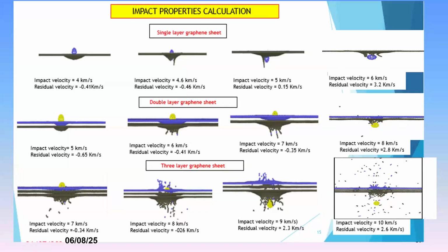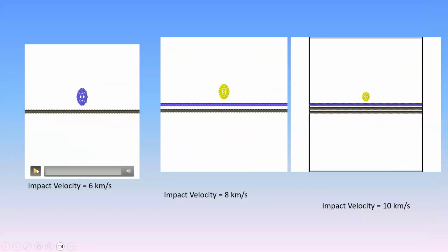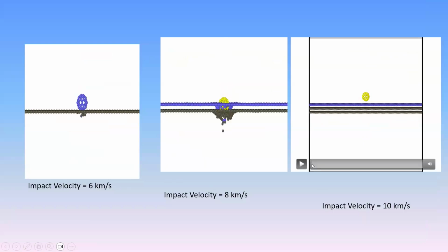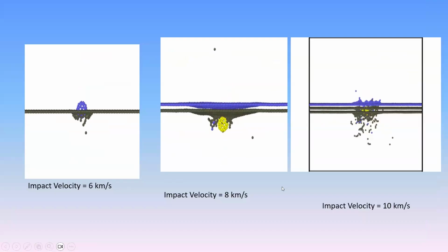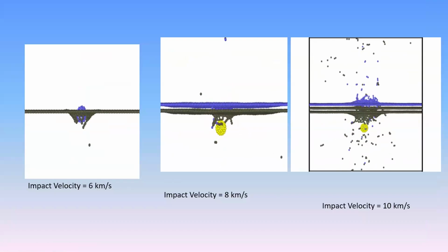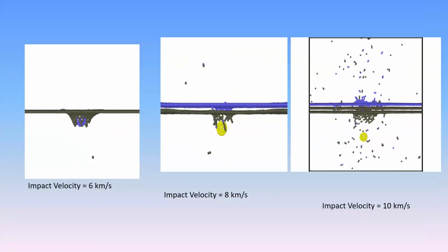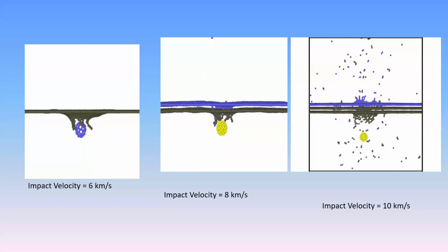So we also find out the residual velocity. Already we discussed what residual velocity is in the earlier slide. So in that way, you have to find out the residual velocity and impact velocity, whether it is breaking the graphene sheet or not. In these simulations, you can easily see what is happening. So 6 kilometer per second just breaks the one layer. 8 kilometer per second, you break the two layer. And 10 kilometer per second, it breaks the three layer. So in that way, you can easily identify.